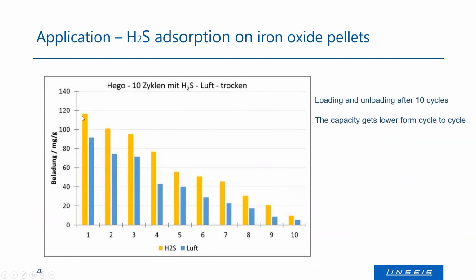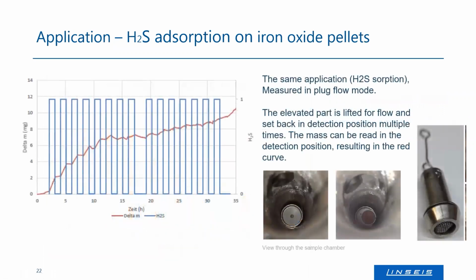And then, as you can see, from cycle to cycle, there's more sulfur gathered at the surface of these pellets. And therefore, the loading and unloading gets smaller from cycle to cycle. And this graphic shows finally that about 7 to 8 cycles is useful. And then if you go to 9 and 10, there's almost no reaction anymore. And therefore, you have to regenerate or to waste your pellets after 10 cycles. And out of this data, you can try to optimize the structure of these pellets. You make them more porous, you give them more surface. Maybe you get rid of the sulfur in some way. And this is why such experiments are done, because it helps to optimize this process.